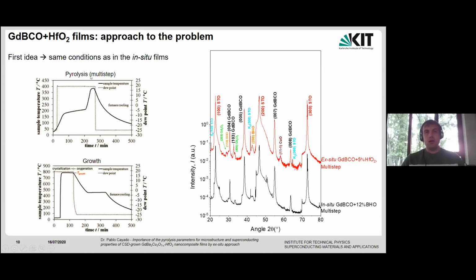We call it multi-step because it's quite complex and has several steps because of different internal reactions that happen during the pyrolysis. And then we use the conventional growth. But here, when we analyze the XRD, we observe that while in the in situ approach, the conventional films, we have a nice film with only the presence of the epitaxial peaks, so 00L peaks, when we use this combination of processes, we observe a huge 103 peak, which means that we have a lot of misoriented grains.